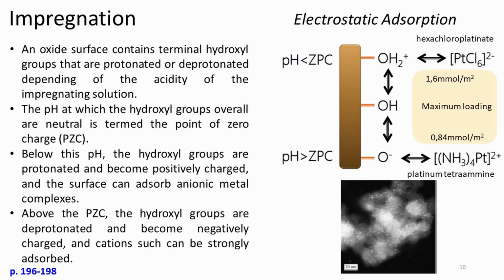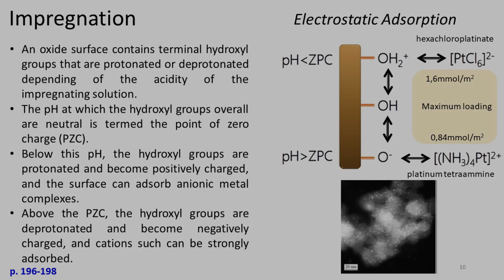The method is particularly attractive for deposition of the expensive noble metals such as rhodium, platinum, or palladium. Ion adsorption is carried out by contacting the support particles, which can be powder or bodies, with a large excess of dilute solution of your metal precursor. After proper equilibration, which is important when you use millimeter-sized support bodies, the loaded support is washed to remove non-adsorbed species and then dried. It is very important to carefully select the pH of the solution with respect to the point of zero charge of your specific support, in combination with the charge of the metal ions in solution.